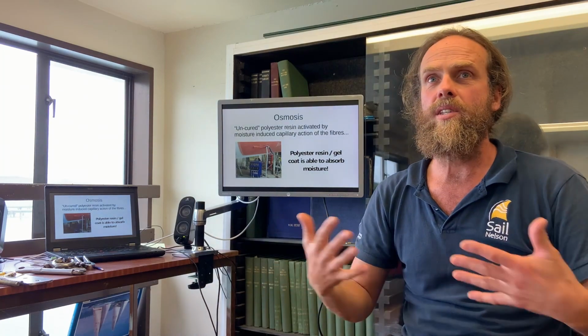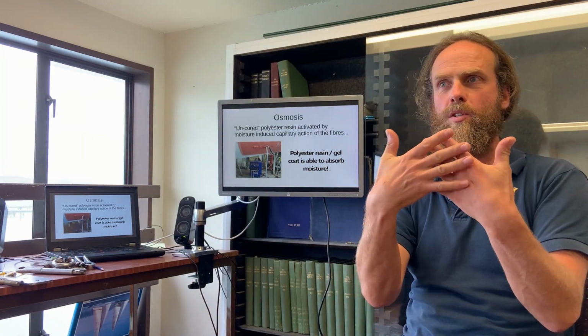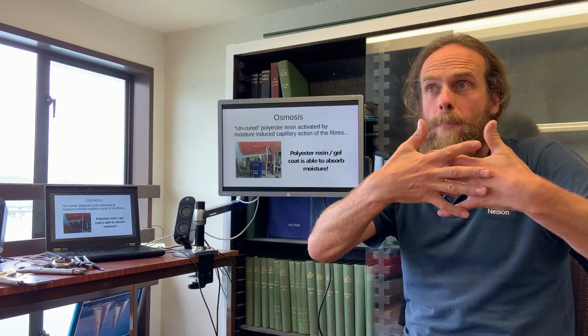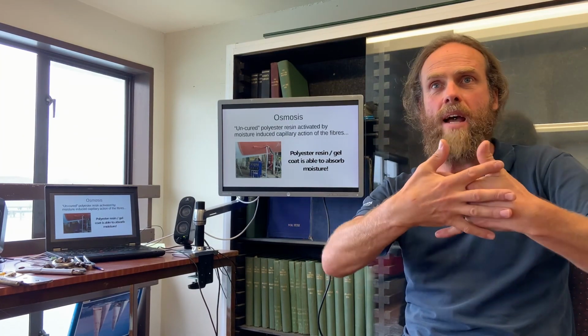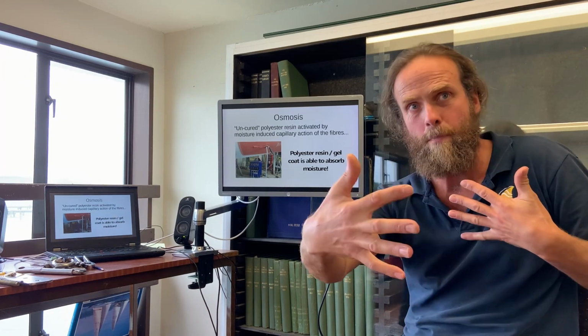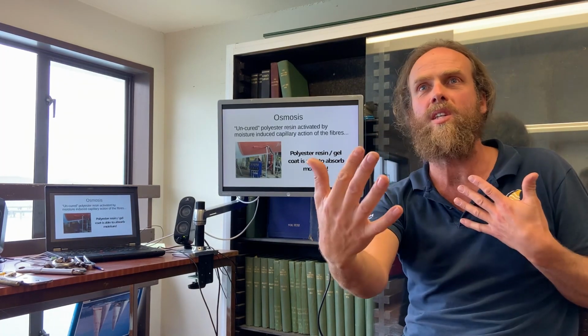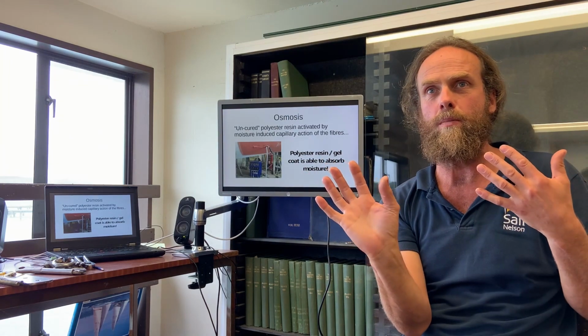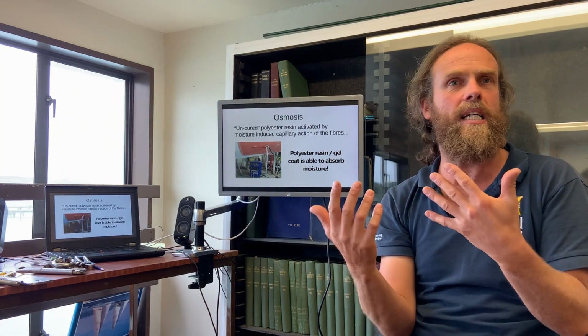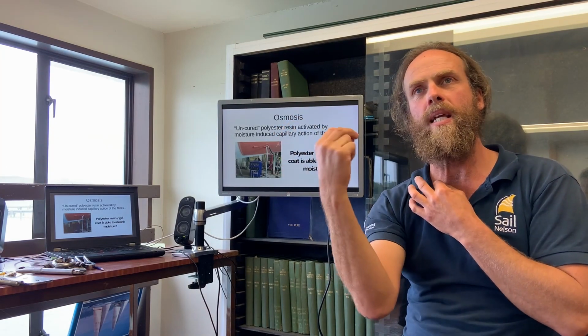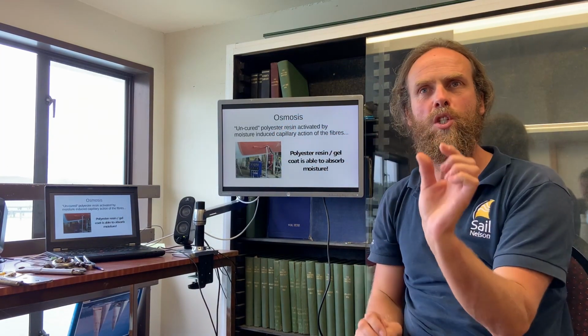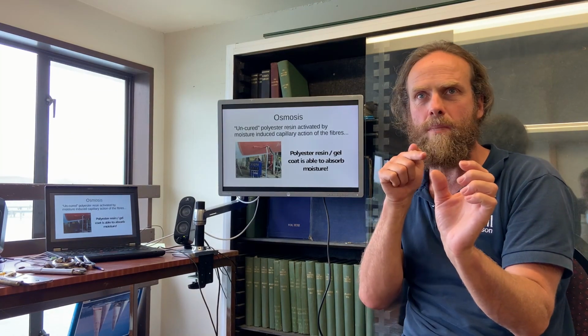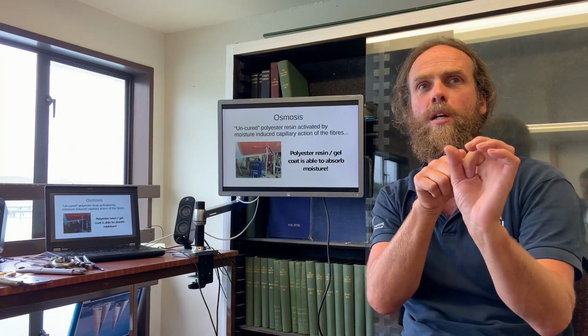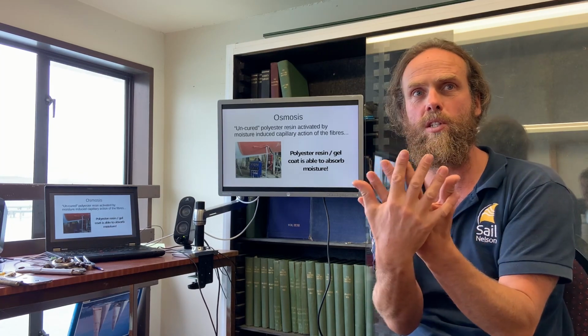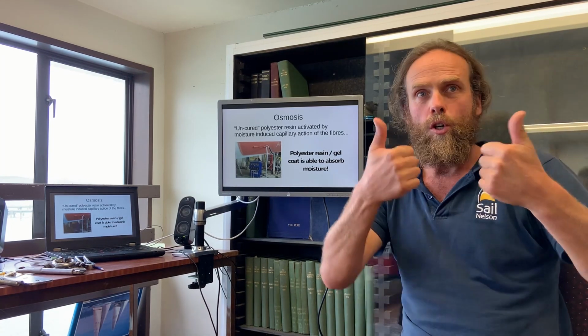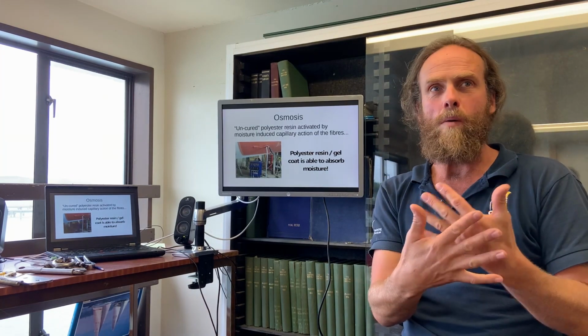At its worst case, that tracking that we talked about into the substrate laminate can actually blister and blow apart, form large cavities, high pressures, and actually pull the laminate back apart. That's the worst case scenario, where you get large delamination due to osmosis, all right? Again, both things are exactly the same. What it means is that in a simple construction, you've got solid enough substrate that the moisture hasn't been able to track into, or there isn't any soft substrate down in the laminate. It's just at a superficial layer, right? Good. I haven't got massive delamination.